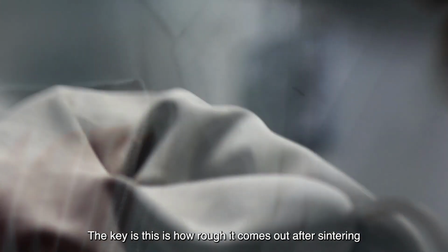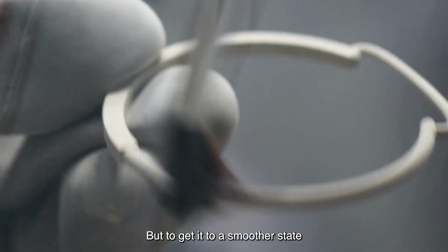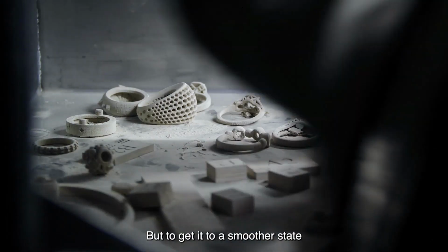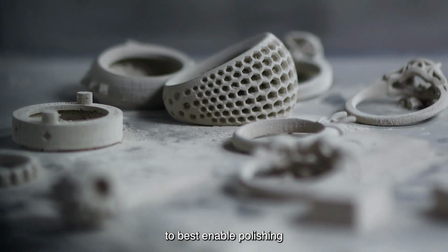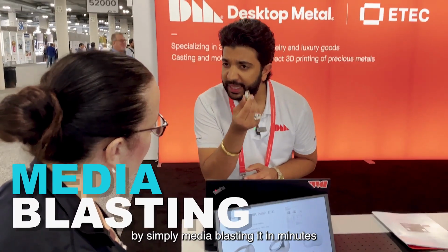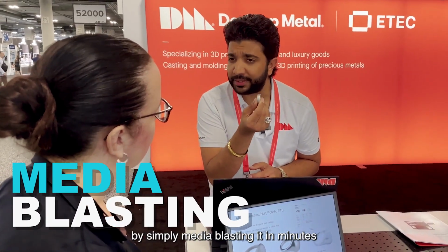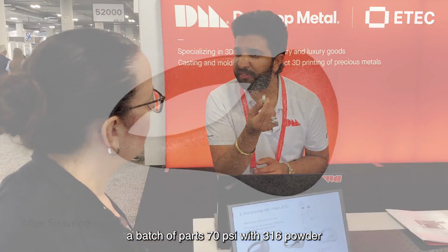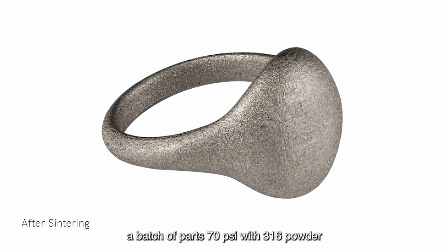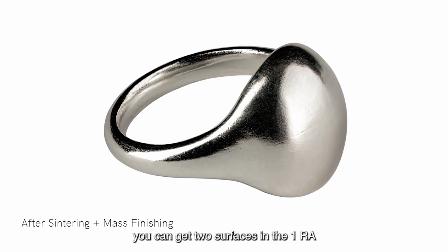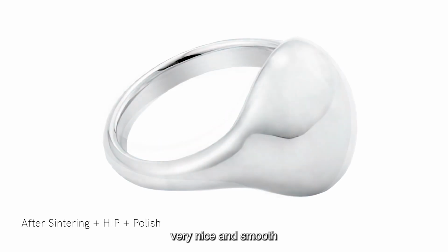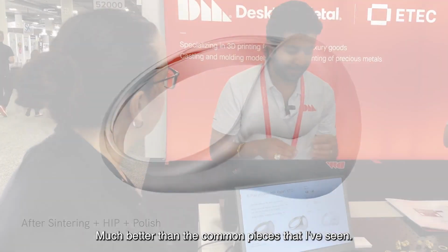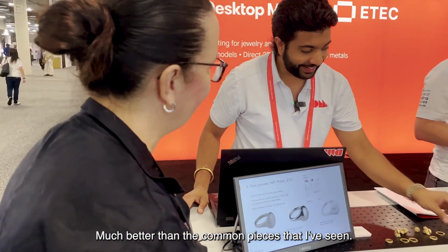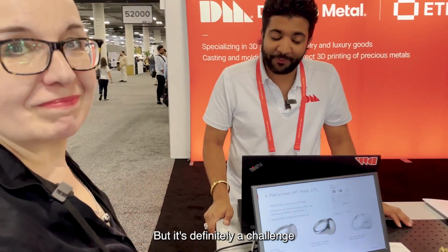The key is, this is how rough it comes out after sintering, but to get it to a smoother state to best enable polishing, by simply media blasting a batch of parts in minutes, at 70 psi with 316 powder, you can get to surfaces in the 1 Ra range very nicely. That's amazing. That's much better than the common pieces that I've seen. Thank you. But it's definitely a challenge.